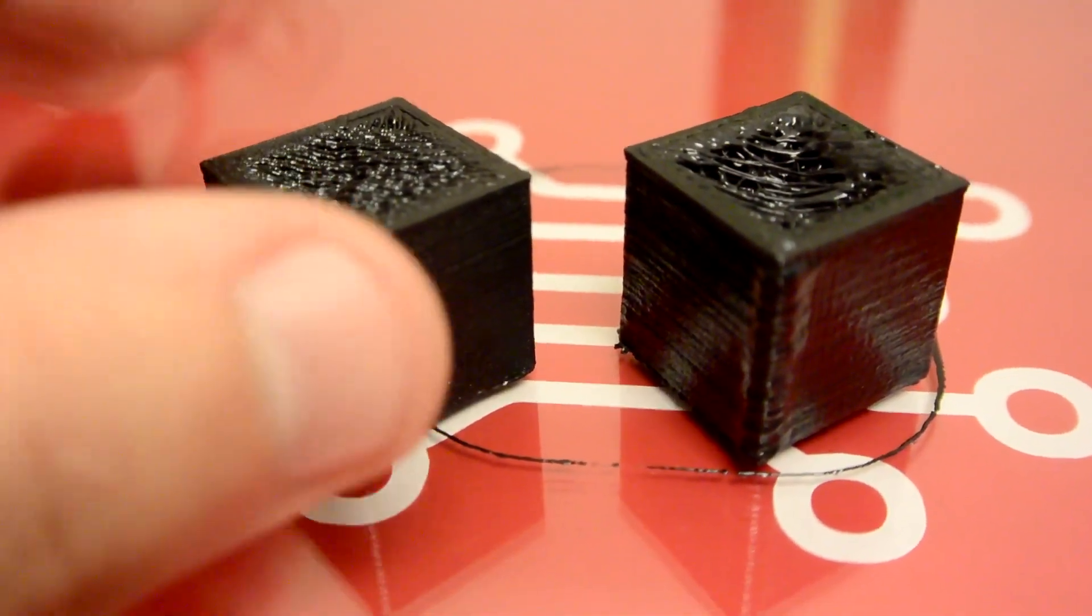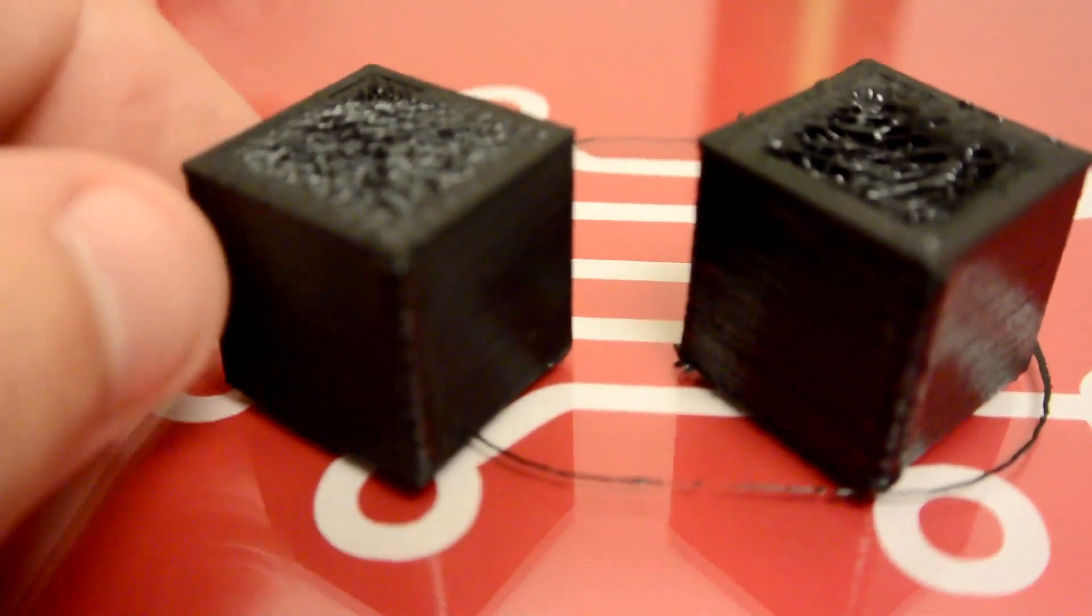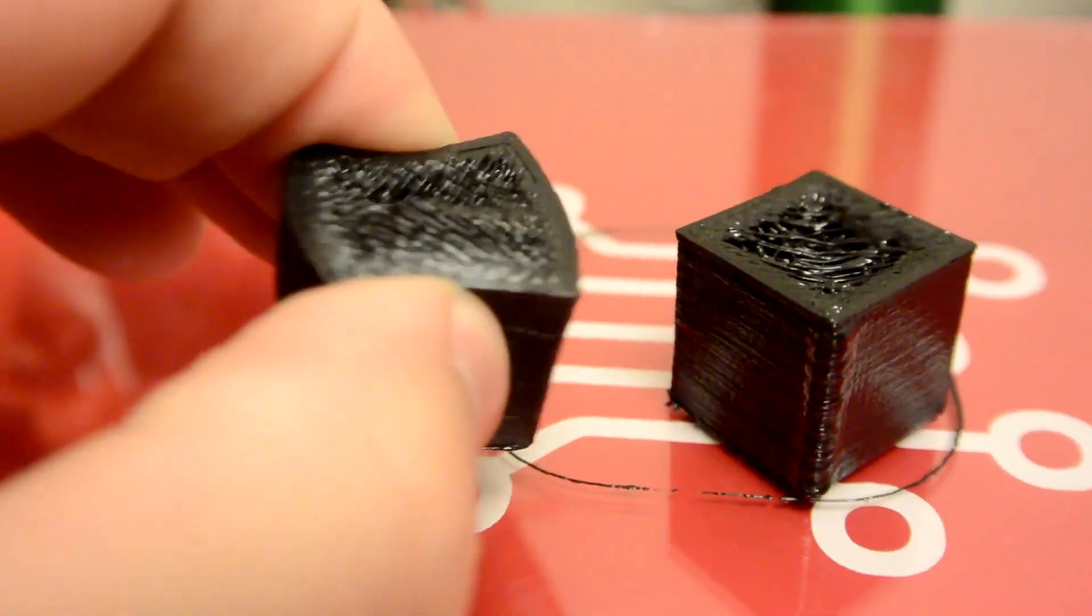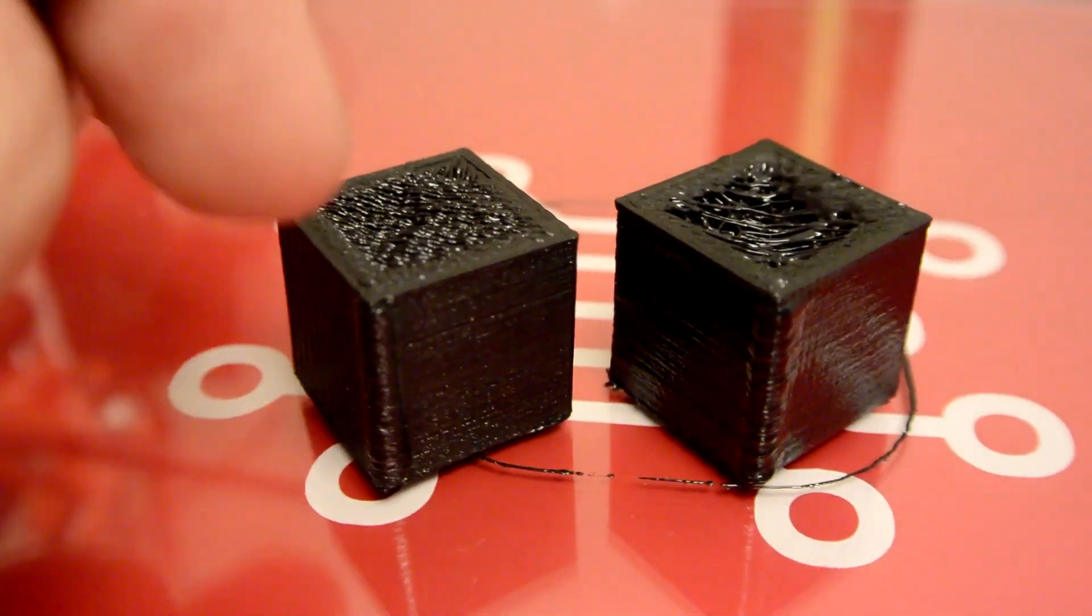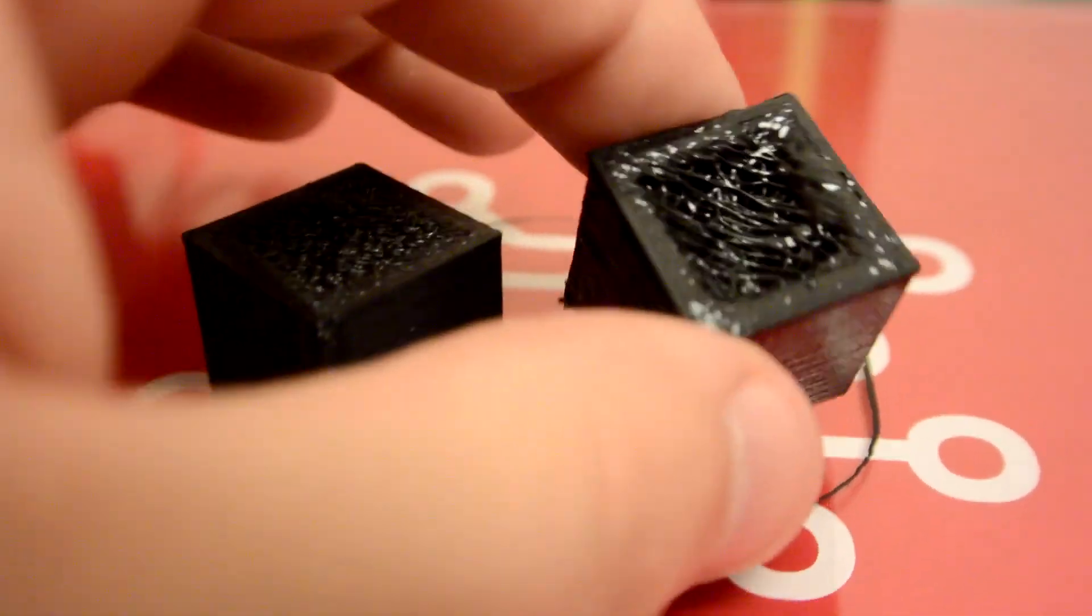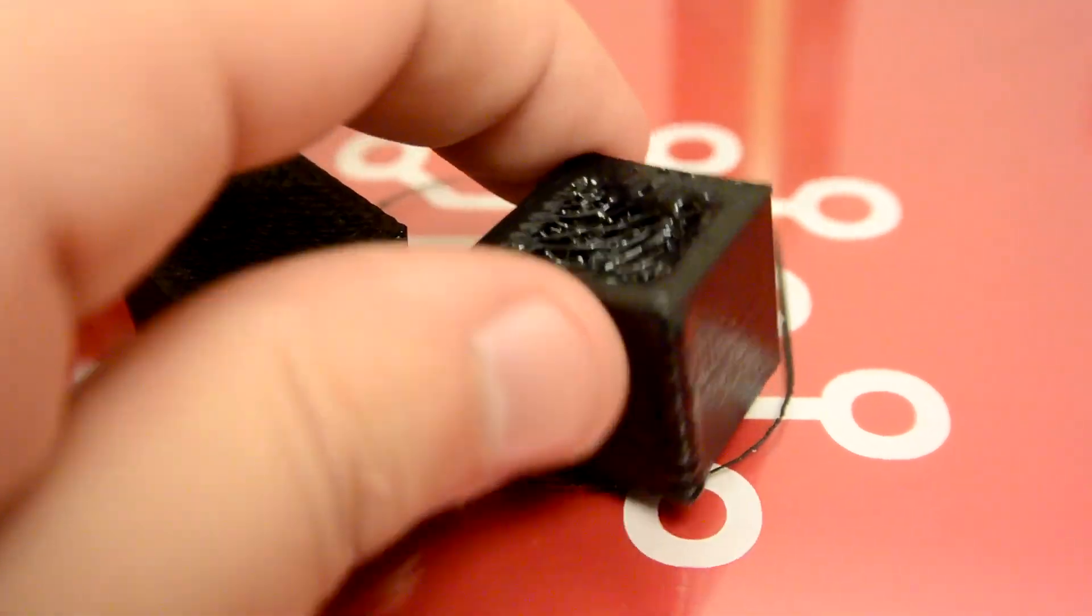So the print just finished. On the left here, I have the print that just came off the print bed that had the fan going the entire time. And on the right, I have the last best calibration print before I put the fan on. And I can tell you guys that the fan makes such a big difference. So first I'm going to point out the top, the quality of the top layer here. So this is a completely hollow model. There's no infill whatsoever. So these top layers are just printed over nothing. It just prints in air, and then the layers eventually build on themselves. And there's five layers on here. So you can see that without the fan going, the Filaflex just oozed everywhere. And it left quite a dimple in the top. And there's just, you can't even tell that it's supposed to be solid. You can see right through it. It's pretty bad.